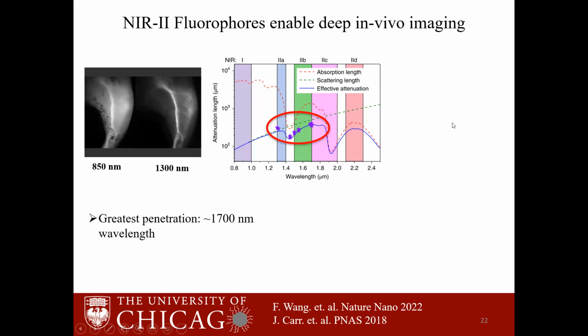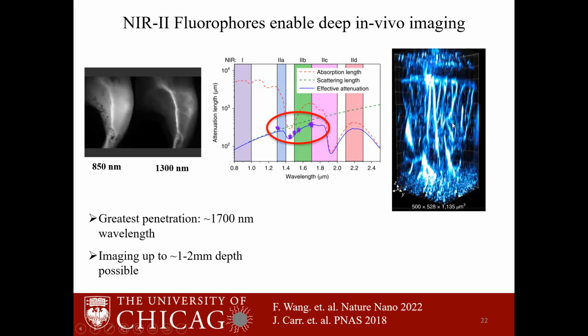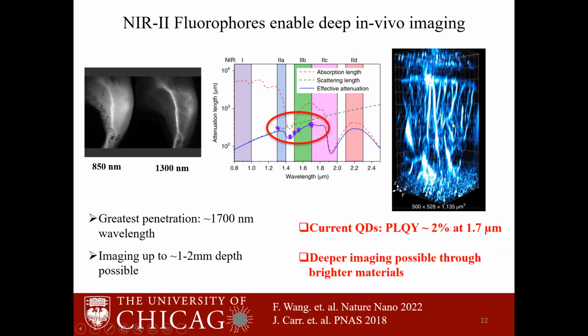The wavelength region where there is a compromise between the scattering and the absorption is the shortwave infrared between 1.3 and 1.7 microns. And 1.7 micron is the wavelength at which tissue has the greatest penetration. The Hongjie Dai group have used quantum dots emitting at 1.7 microns to do live imaging within the brain tissue, and they can achieve a penetration depth of 1 to 2 millimeters. But the biggest challenge of the current quantum dots emitting at 1.7 microns is that their quantum yield is extremely low. It is only 2%. So if we can get brighter quantum dots, say 100%, this will more than double the penetration depth that is possible, and this can answer a lot of biological questions which were not possible before.